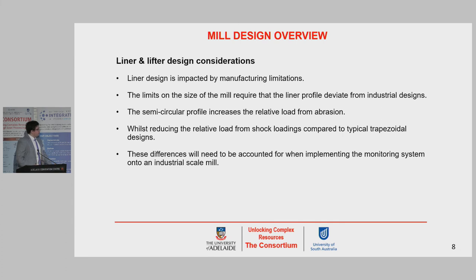the limits of the size of the mill require that the liner profile deviate quite a bit. So there's a semicircular or more hemispherical profile that's used instead. That's more optimal for this size of mill. However, that does increase the relative load from abrasion, which isn't so useful with these accelerometers, and it would reduce the shock loading from the impacts of the ore charge falling onto the toe of the charge in the mill. This is when compared to traditional trapezoidal designs used in industry. So that will be something that will need to be accounted for with my report later.